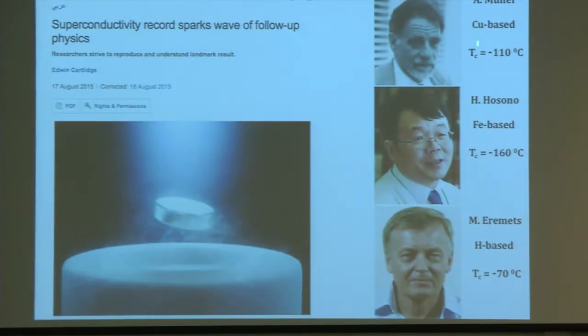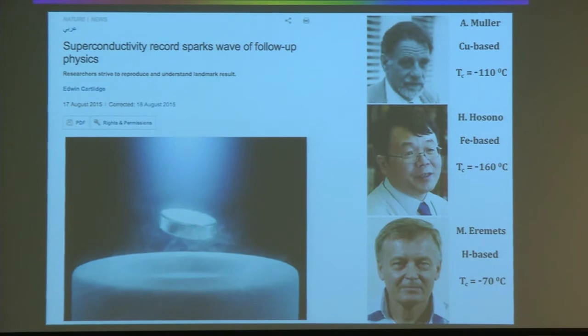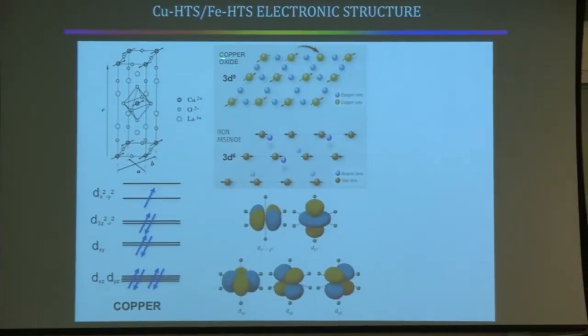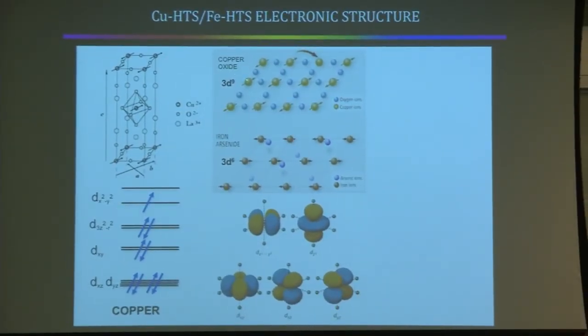Okay, so now for the ugly reality. We have two compounds with which we can work to try and understand what's going on. One of them is copper oxide, a square lattice of copper, oxygen, copper, oxygen. And the crystal symmetry is an octahedron of oxygen atoms surrounding the copper. And that lifts the degeneracy of the d orbitals in the copper atom such that the dx squared minus y squared orbital is on the top of the manifold.